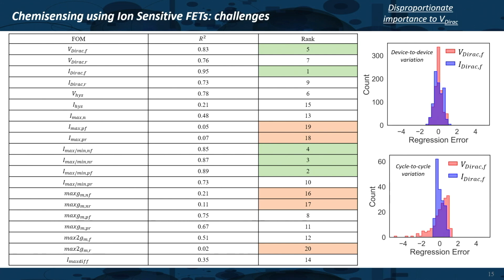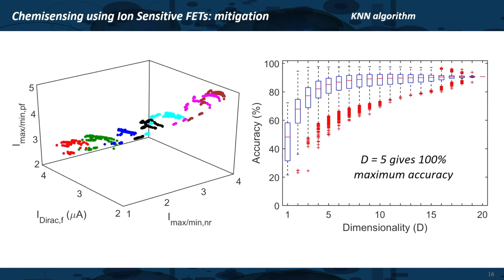Now, what we could do is some very simple machine learning, where instead of looking into one parameter at a time, why don't we combine 3 different quantities? Let's say the top 3, and there you see that you get clustering of the data. This is the k nearest neighbor algorithm, and you get to almost 100% accuracy once you look into 5 different parameters at the same time.